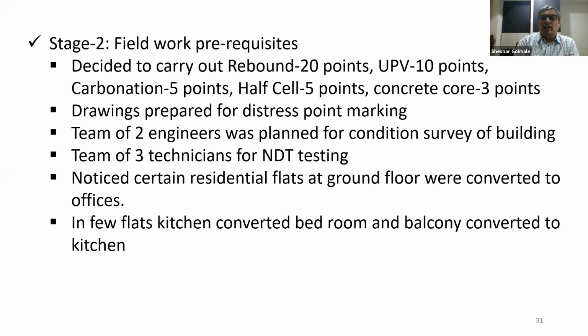Stage 2, we decided to carry out rebound points 20, ultrasonic pulse velocity 10 numbers, carbonation 5, half cell 5, and concrete core 3 points. Drawings were prepared for the distress point marking. Then a team of 2 engineers was planned for the condition survey of the building and a team of 3 technicians for NDT testing. We noticed certain residential flats at ground floor were converted to offices, and in a few flats the kitchen was converted to bedroom and balcony converted to kitchen. These were the additions or alterations done in the building that we noticed in the stage 2 inspection.